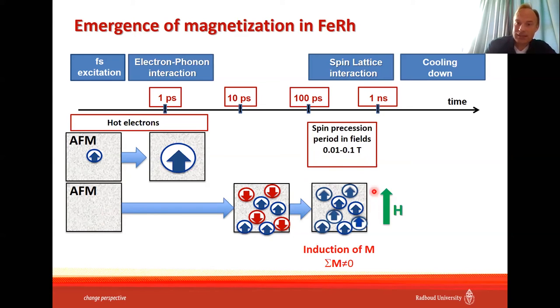That time scale of 100 picoseconds is given by the characteristic time of spin precession in this field. So it takes about 10-20 picoseconds to generate ferromagnetism, and it takes 100 picoseconds in this field to align the magnetization. So basically, this is the answer which we can give now about the physics of the phase transition in iron rhodium.